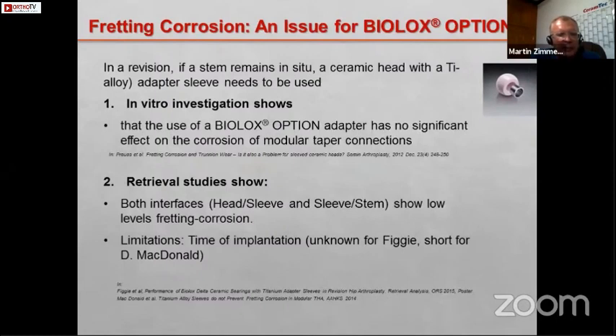But as you can imagine, Ceramtech, before launching this product on the market, has done a lot of testing in vitro, specifically also about the fretting and corrosion. And what we can see with up to 10 million cycles, there was no occurrence of fretting or corrosion, thanks to the fact actually that the sleeves were made in titanium, aluminum, vanadium alloy.